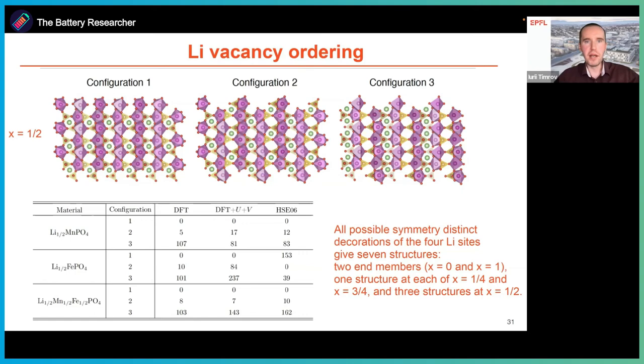So what we did, we computed the total energy of each of these configurations and figured out which one of them has the lowest energy. And it turns out that configuration one has the lowest energy in all three materials and all three methods, except one, which is the iron olivine, where in the case of the hybrid functional, configuration two is the lowest in energy. But for all the rest, we systematically find that configuration one is the lowest in energy. And then we computed the formation energies.